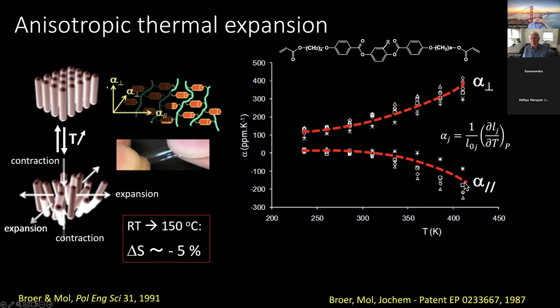And negative is not so bad, because that leads to tensile stresses on the fiber, which even keep them more straight as needed. So on the other hand, in the direction perpendicular to the fiber, of course, we have a high thermal expansion coefficient. The volume thermal expansion coefficient of these materials is comparable to normal polymer materials.